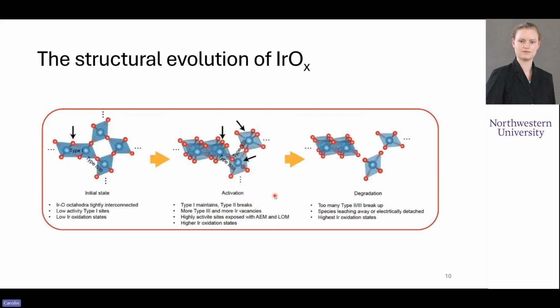And then over time, that same change continues until you reach a point where there's too much breakage of the type 2 and 3 corner sharing octahedra, which then leaves individual species that can leach away or become electrically detached from the base electrode. And so that is how the same kind of structural transformation and degradation first increases and then decreases activity until